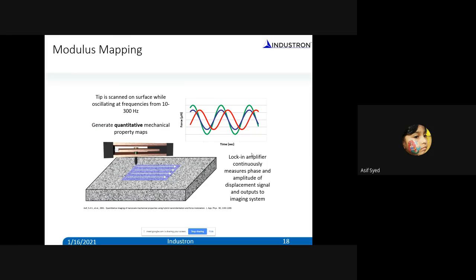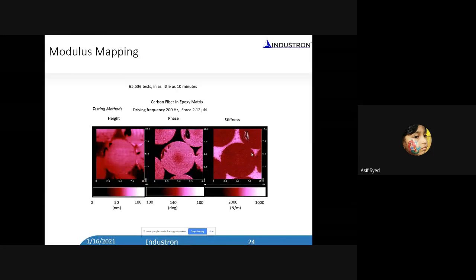Okay. Now, instead of measuring at one location, like I mentioned with imaging, you can also scan on the surface as you do this modulation. I mentioned that you have to oscillate the force and measure the displacement response. You do that as you image the surface, right? You can measure the stiffness as a function of position, and with that, you can create maps, okay? For example, this is a property map.